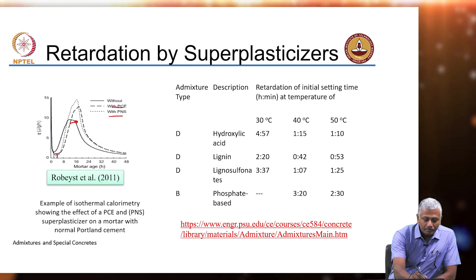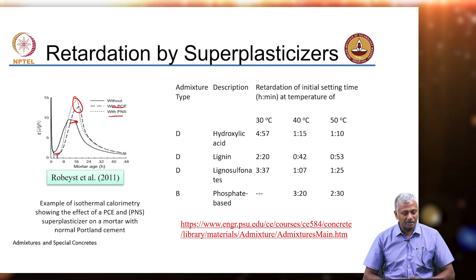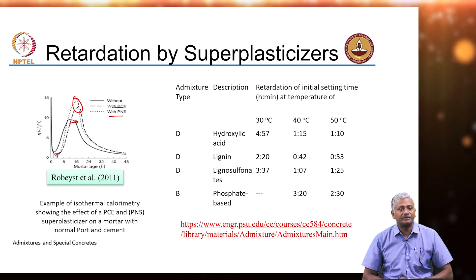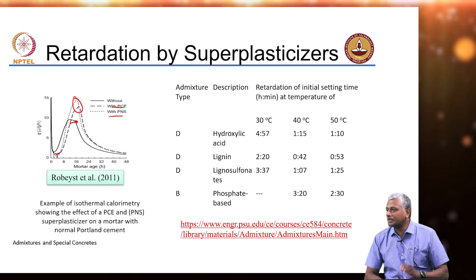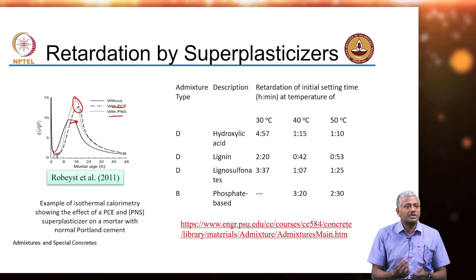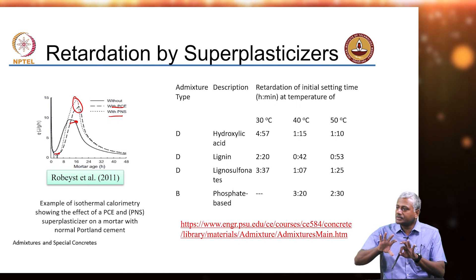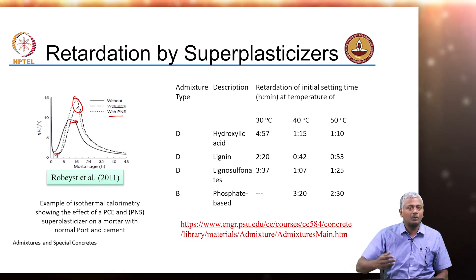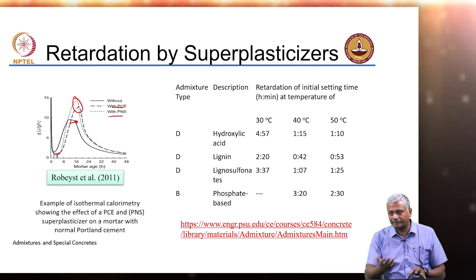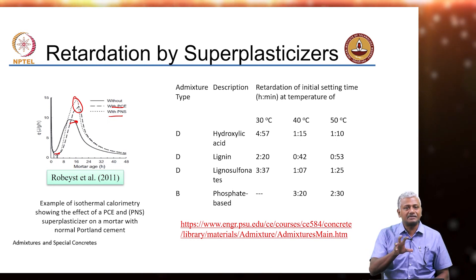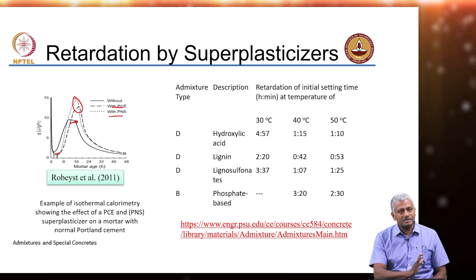Interestingly, the peak heat rate is higher when superplasticizers are used, even though the dormant period is extended. The reason is that in the presence of superplasticizer, particles are well dispersed, so each particle has better access to water. This allows rapid dissolution of C3S to occur quite significantly, which is why the heat rate goes up — but the time at which this peak occurs is extended.